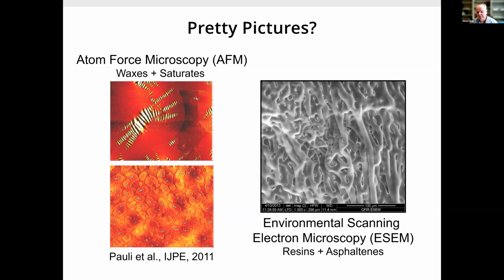That structure would form a gel at low temperature, and you would crystallize even more waxes if you have a poor quality asphalt binder. That wrecks your road when it is gelled. The thermal stresses in the winter don't relax. And then the oils in between those crystals squeeze out like a sponge.